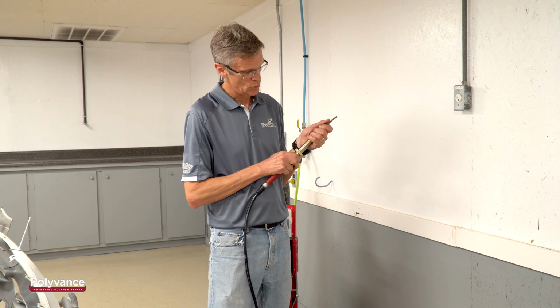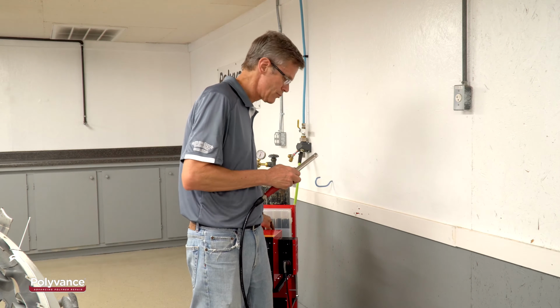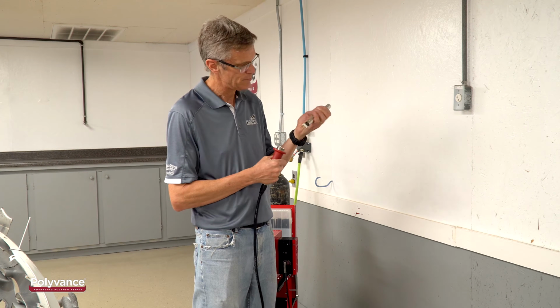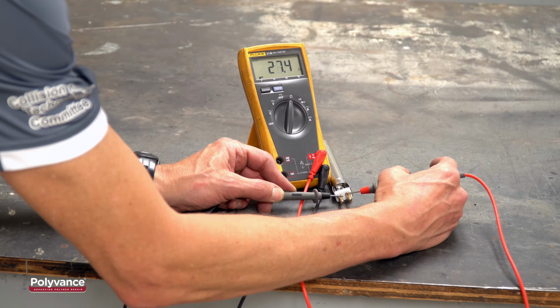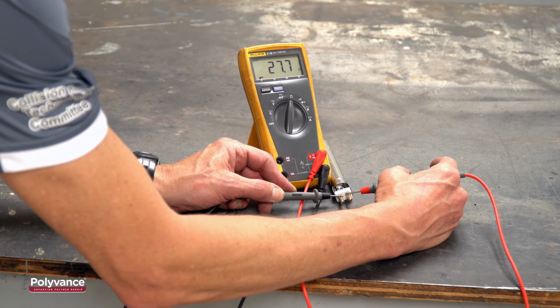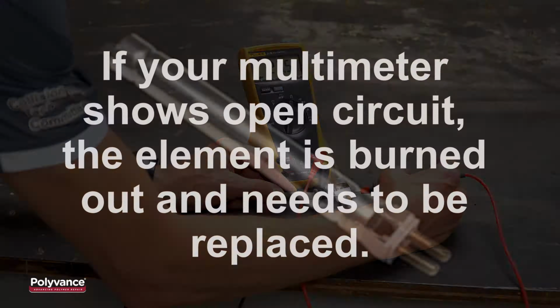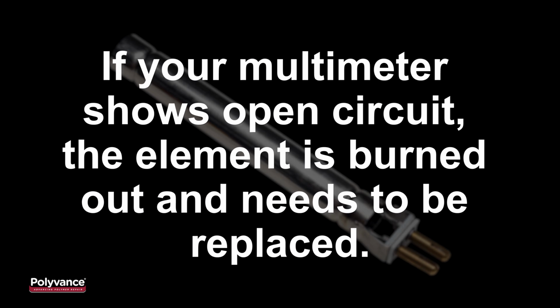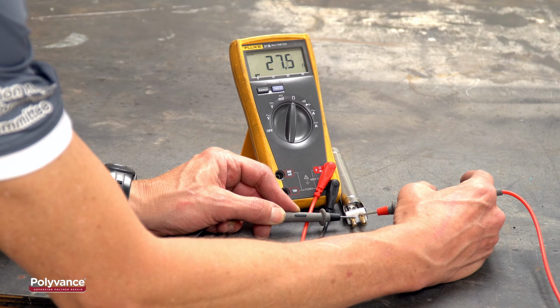If the nitrogen welder doesn't get hot at all and the green light is glowing, most likely you have a burned out heating element. Unplug the welder, then remove the heating element from the handle. Check the resistance of the element across the two pins. It should be about 26 ohms. If your multimeter shows open circuit, the element is burned out and needs to be replaced. If the element shows 26 ohms and still doesn't get hot, call Polyvance for technical support.